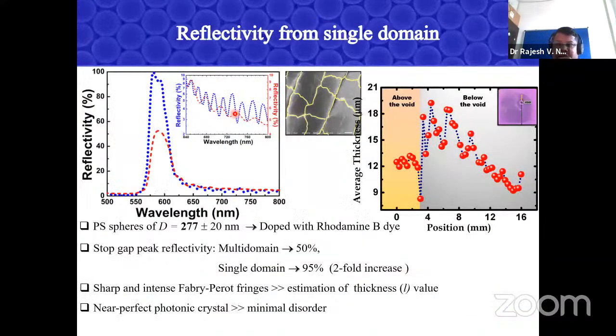Now I have this sample with these kinds of grain boundaries. I mounted this sample and measured the reflectivity as a function of wavelength in our own setup, the setup we just showed in the last slide. You can see that the reflectivity goes up to 100%, which is a very nice reflectivity. And if you measure the same sample in a commercial spectrophotometer, because of the large beam size, the result is much reduced, just like 40 to 50%.